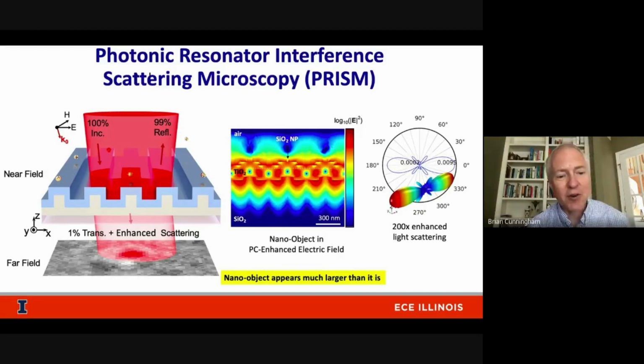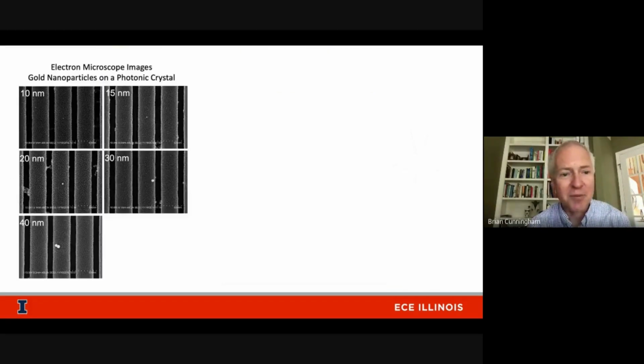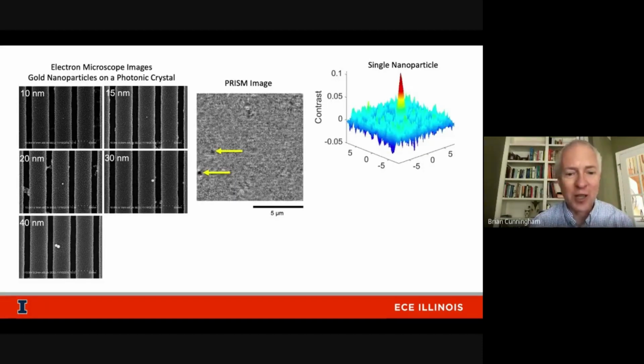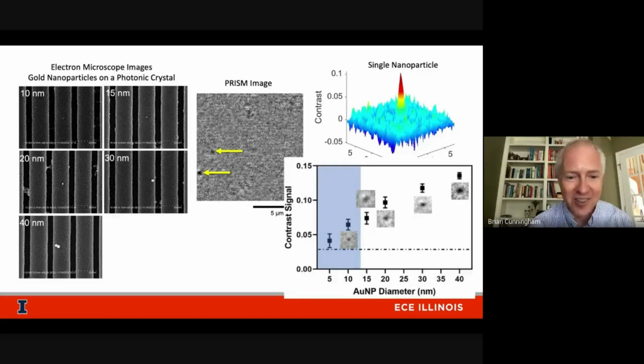And so even without using any labels, we can count things like gold nanoparticles by their enhanced scattering. So with this method for enhanced scattering, here we can see gold nanoparticles even down to 10 nanometers in size, really small, show up with very nice signal to noise when we detect them by their scattered signal.